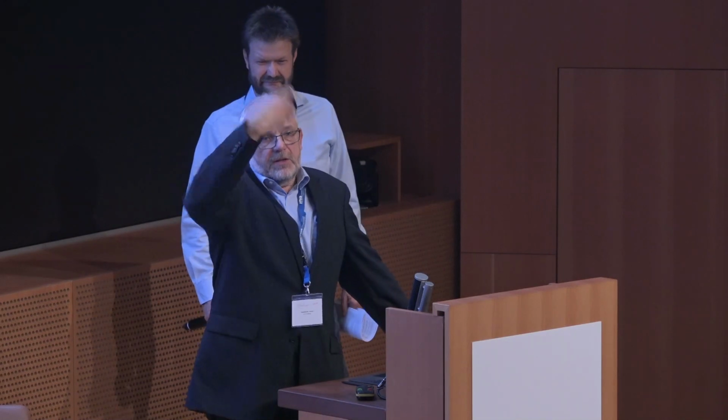Lysolipid has another strange feature, and this is that it's not doing flip-flop across the membrane. So if you add it on one side, you get into other kinds of trouble with bending membranes. But when you have it in both leaflets, you should tolerate 10% in a fluid membrane without causing too much trouble.